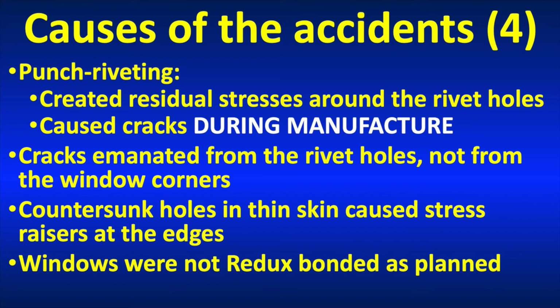Now, the problem with punch riveting is that the rivet itself makes the hole. It's not like you drill a hole and countersink it, put the rivet in and then dolly it or whatever and clinch it up tight. The punch rivet punches the hole, puts the rivet in and does the whole thing in one hit. But it leaves a lot of compressive stresses around the edge of that rivet hole, which then actually caused cracks during manufacture. And we'll see one of those in a moment.